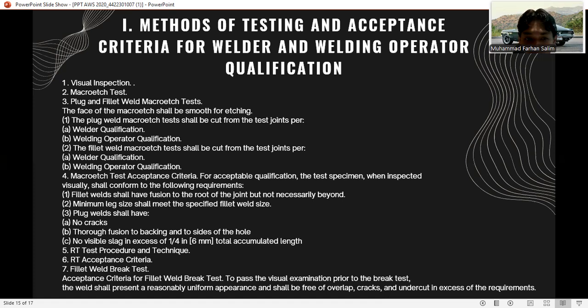4. Macroetch test acceptance criteria for acceptable qualification. The test specimen, when inspected visually, shall conform to the following requirements. 1. Fillet weld shall have fusion to the root of the joint but not necessarily beyond. 2. Minimum leg size shall meet the specified fillet weld size. 3. Plug weld shall have no crack, shall have fusion to backing and to side of the hole, with no visible slag in excess of 1/4 in (6 millimeters) accumulated length. 5. RT test procedure and technique. 6. RT acceptance criteria. And last is the fillet weld break test.